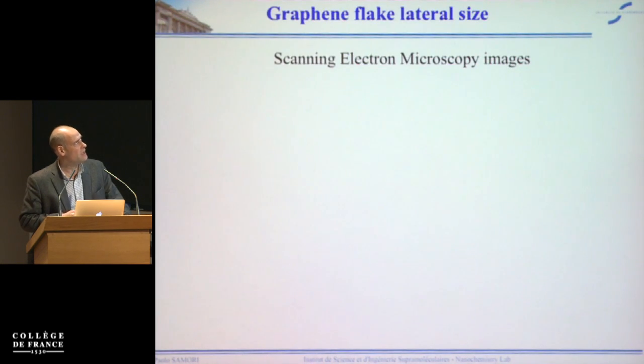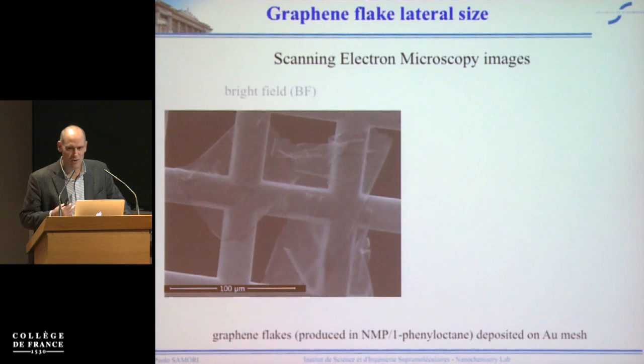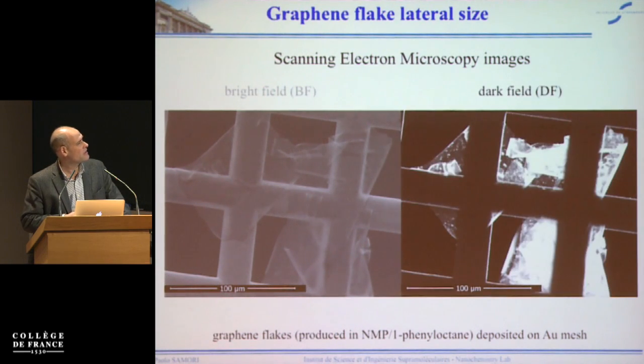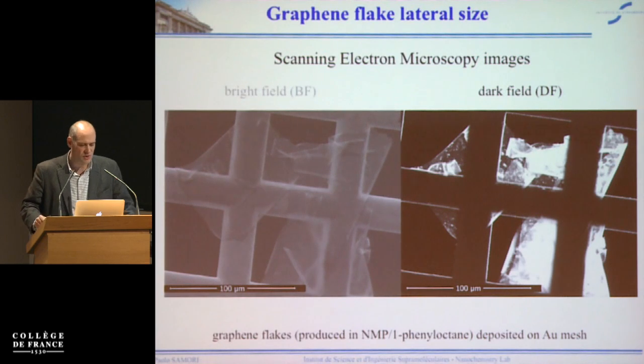You always like also to see how your sample looks, and so by SEM, by comparing the bright to the dark field, we can see there is a single flake here with a size of about 30 micrometers, and actually the comparison of the contrast in bright and dark field suggests that this is a single-layer thick flake processed from solution in NMP.